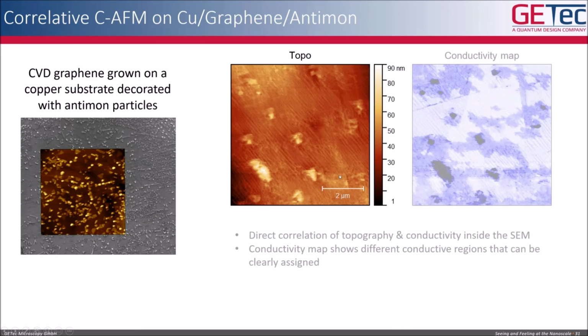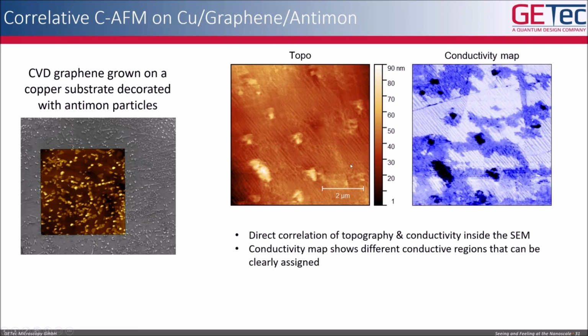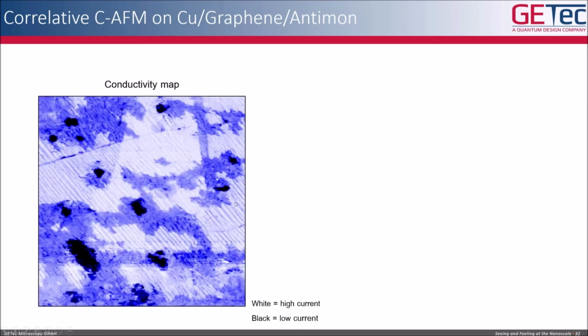Now I want to show you the conductive and topography signal from one of these areas. Here you see the topography, and if you look at the conductivity map, it shows a lot of different conductive regions that can be clearly assigned to different parts of this sample. Let me show this in a little bit higher resolution. The white parts in this conductive signal mean high current, so high conductance, and the black part means low conductance.